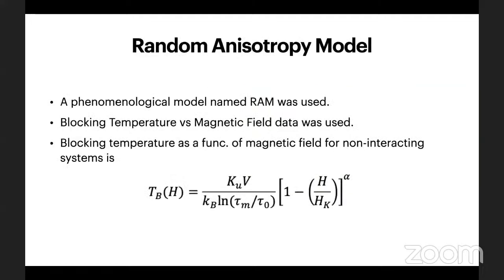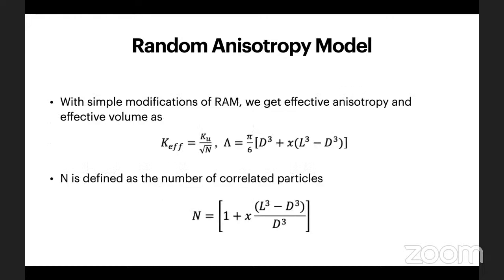So what did we actually do? We have adopted the random anisotropy model that includes interaction effects into account, and we imposed our experimental blocking temperature versus magnetic field data onto that model. This below equation is based on studies reported for non-interacting models. Here, Ku is the uniaxial anisotropy. From RAM, we can conclude with the following equations for effective anisotropy and effective volume. Here, N is the number of correlated particles that is defined by the below equation, and D is the diameter of the sample particle, and L is its corresponding correlation length. Here, X is the occupation percent in the structure matrix.